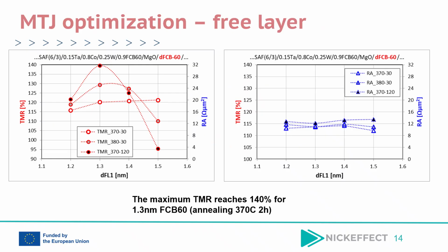The final optimization step focused on the thickness of the first layer in the dual FCB three-layer system, while the thickness of the second one was kept constant at 0.5 nanometer. The objective was to maximize the TMR ratio while maintaining favorable MTJ transport properties. The graph shows the dependence of TMR on the thickness of the first FCB layer for different annealing conditions. For all investigated annealing processes, the TMR ratio exhibits a clear maximum for a FCB thickness close to 1.3 nanometer. Further increase of the FCB thickness results in gradual degradation of the TMR ratio, which is associated with weakening of the perpendicular magnetic anisotropy and degradation of the spin-dependent tunneling properties at the FCB-MgO interface.